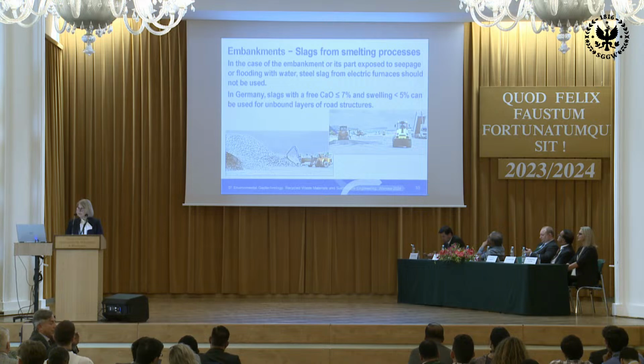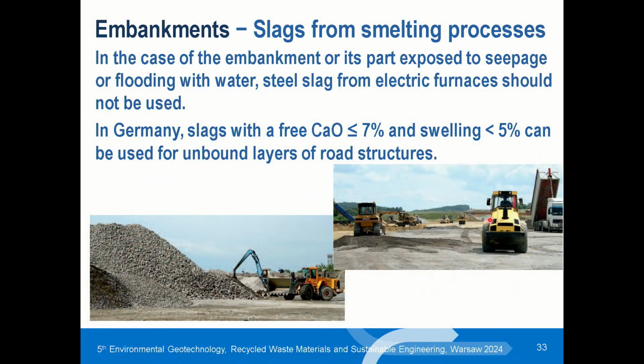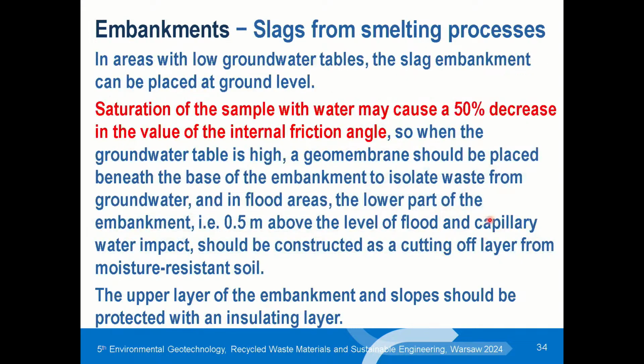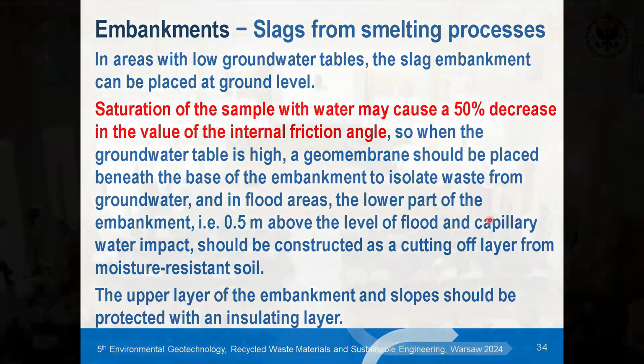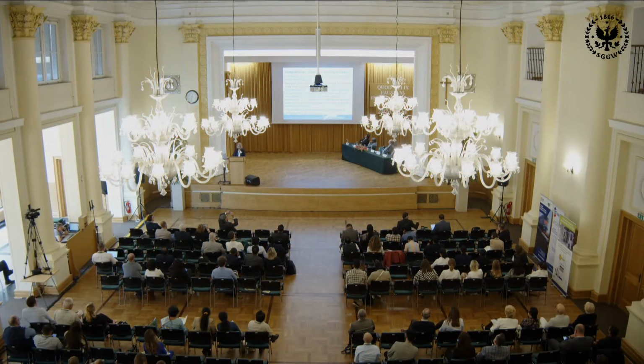The next is slag from smelting processes. I said earlier that we have a problem with irrigation of this material too. So they should be incorporated in the same way as fly ash, because saturation of the sample with water may cause a 50% decrease in the value of internal friction angle. So on flood areas, we should give the cut-off layer too and incorporate material above the level of flood.